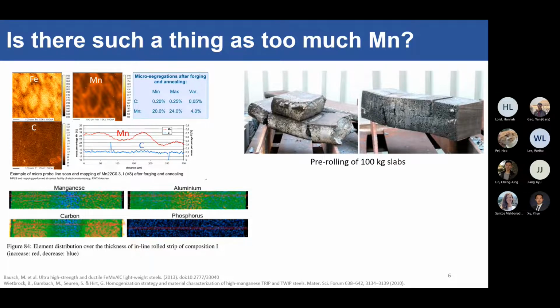So if you cast a very high alloy steel, you get massive segregation to the interdendritic boundaries. This is some work by Aachen University. They have this really crazy forging annealing strategy to try and homogenize the ingot. And you can see that there is a large variation in manganese even after their homogenization strategy. What this means is that you have different stacking faults in your austenite phase, and it's not the same. So locally, you have different TWIP effects going on, and that's not good.